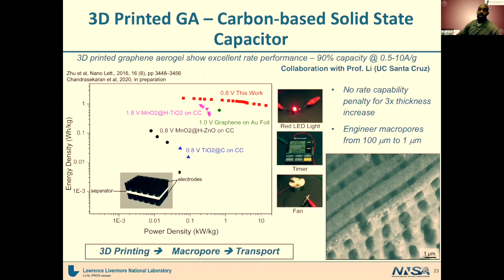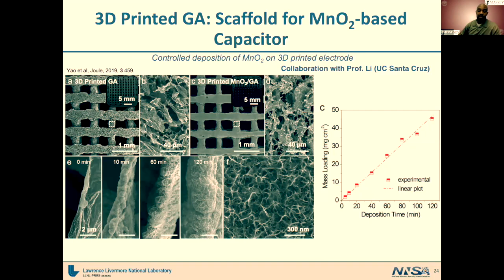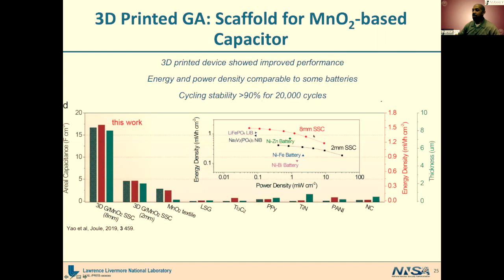We wanted to be able to actually boost the overall capacitance that we can get to. And so here's one way of doing that, adding a pseudocapacitive material. So this is a material that has a much higher capacitance, but is an insulator. So you don't want to use it by itself because it then would be very slow because of the high resistivity. So we put that onto our 3D printed lattices. Here showing, we get very good growth again because we do have this in a 3D printed form, and are able to get to very high capacitances with this material as well, and push to higher power densities without having a serious degradation in terms of the energy density.